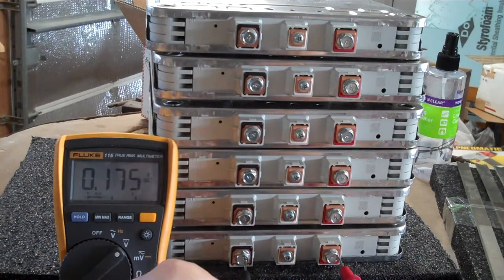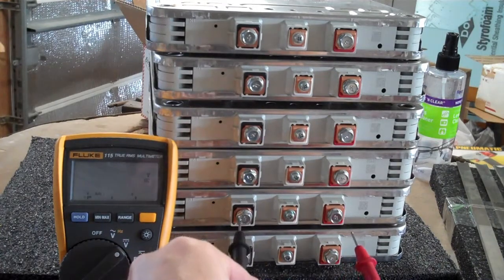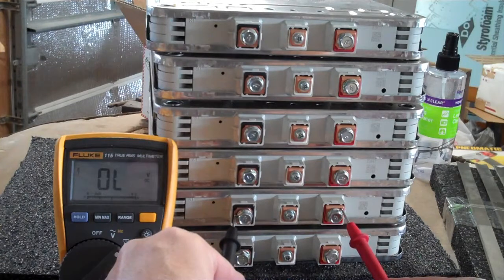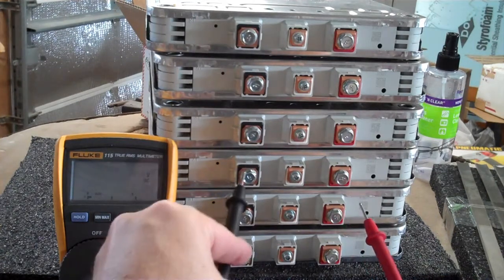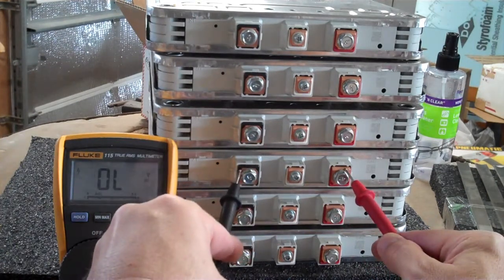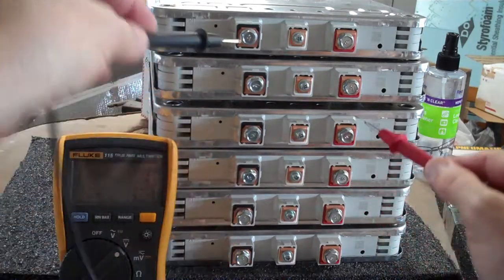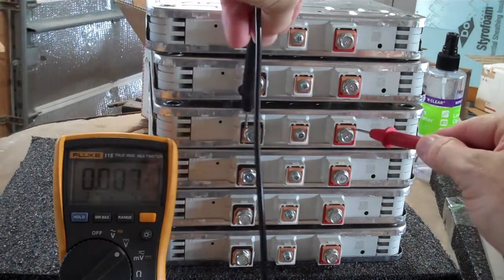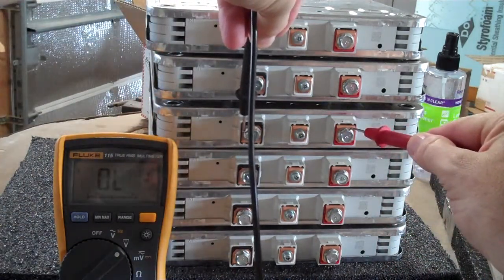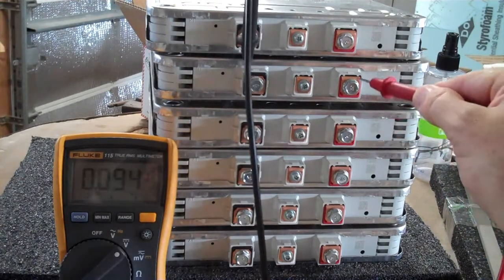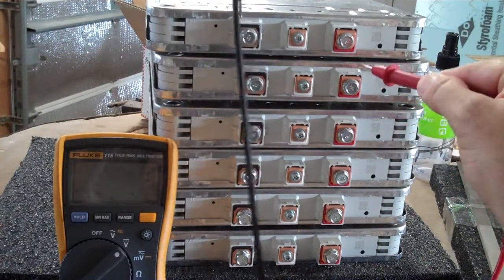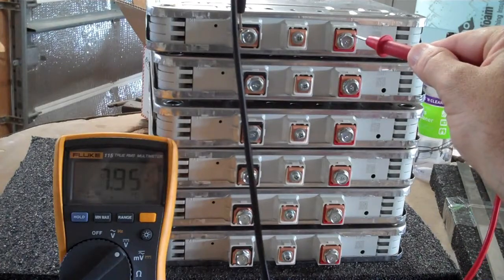This next step is very important. Because we're going to be putting modules in parallel with high current bus bars, we must verify that they are very close to each other in voltage. If you connect two modules that are not at the same voltage, the higher voltage module will charge the lower voltage module at a very high current level until they equalize. This can damage your batteries, spot weld your bus bars in place, or even cause a fire in the worst case. So make sure that your modules start off all at the same voltage.